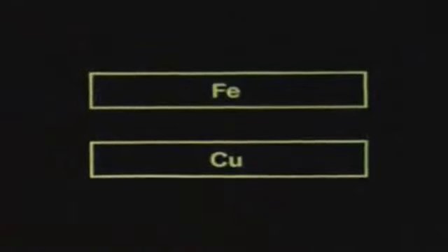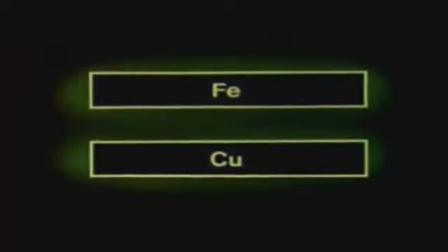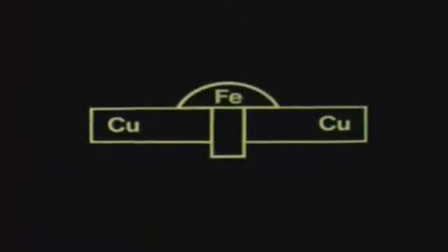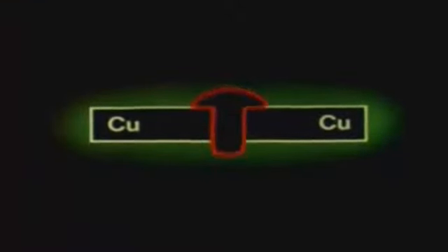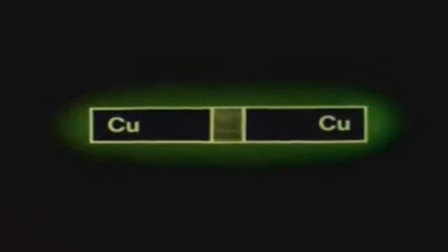We have seen that when metals are placed in an electrolyte, such as seawater or wet earth, each of them may corrode. However, when the two dissimilar metals are brought into direct contact with each other and immersed in an electrolyte, the corrosion of the steel will be accelerated. But at the same time, the copper will have been protected. This reaction is turned to advantage in cathodic protection, used, for example, on underground pipes and ships. On its own, the steel hull would corrode in seawater where paint had been damaged. So, zinc blocks are fitted in good electrical contact with the steel. The steel is protected, and the zinc corrodes. With zinc blocks fitted in the right places, the hull remains intact as long as the zinc is replaced regularly.